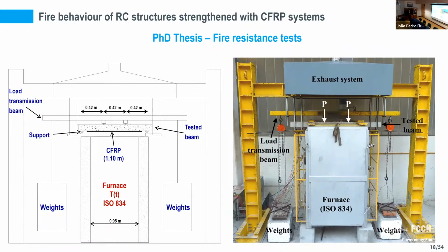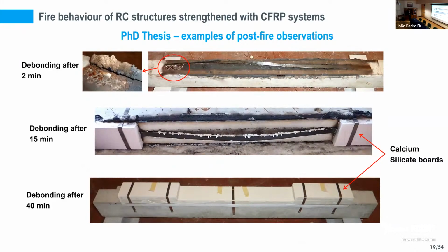So these were the tests that were performed at that time, and some pictures exemplifying what we observed. When the CFRP system was left unprotected, we confirmed that it is very susceptible to fire action. Here you can see that the system debonded only after 2 minutes of fire exposure when left unprotected. Applying the fire protection system only to the anchorage zones, we were able to explore that cable behavior that I mentioned before. And with this, we extended the fire resistance up to 15 minutes.